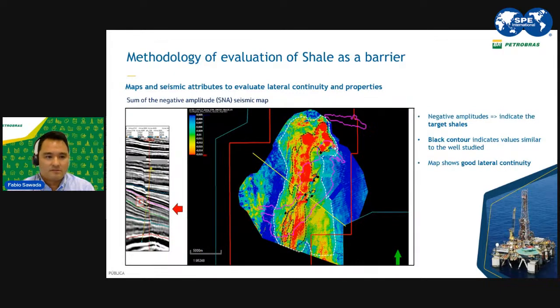Another technique of mapping the continuity, and also whether this formation is prone to form the barrier, would be using the seismic attributes. We also had the help of geophysicists in this work, and they proposed this attribute would be the sum of negative amplitude, and the target shales would be shown here in red. So the red is the shales that have the most potential of forming the natural barrier.